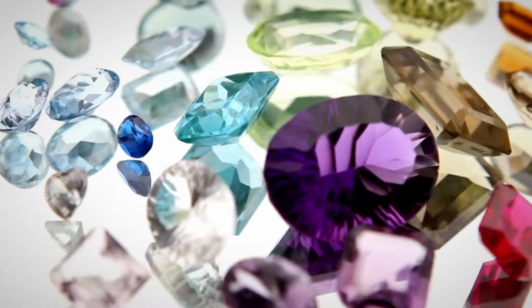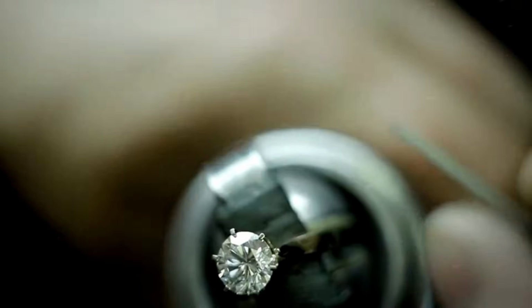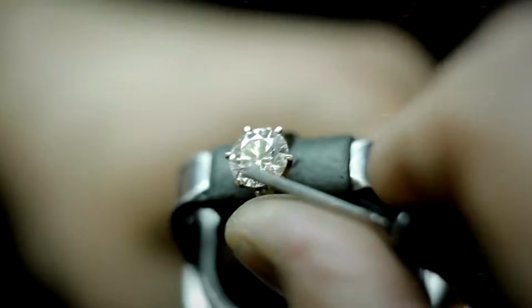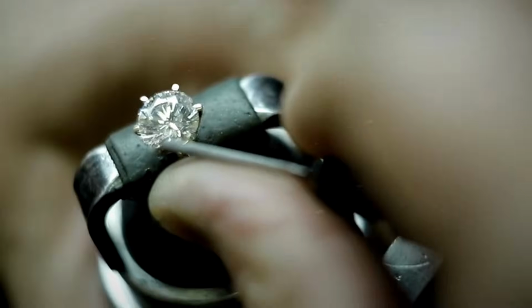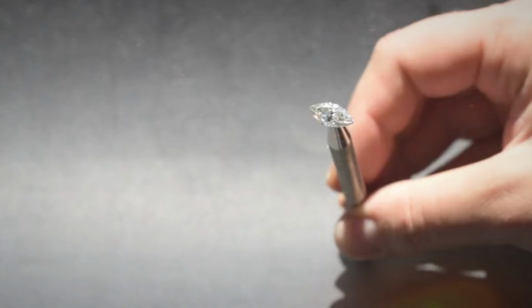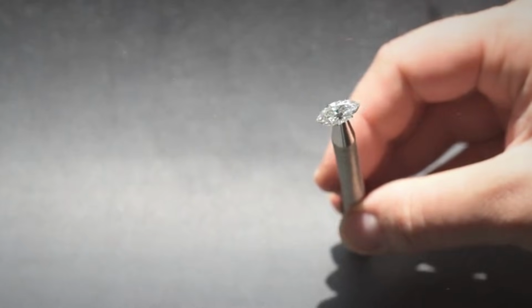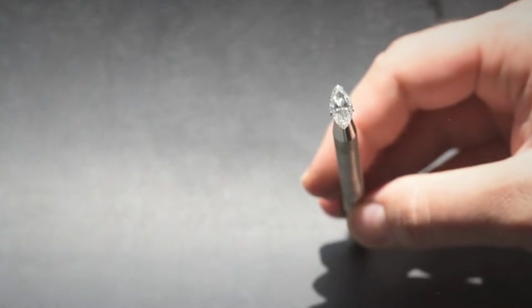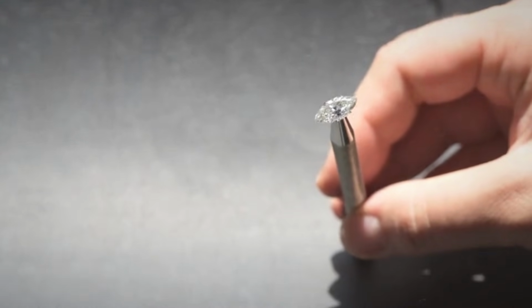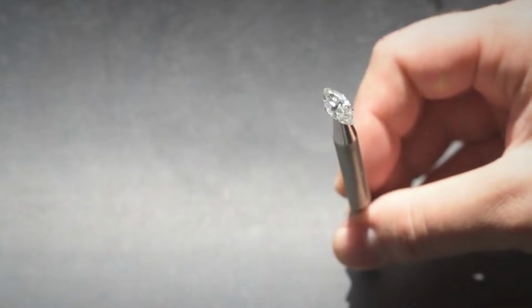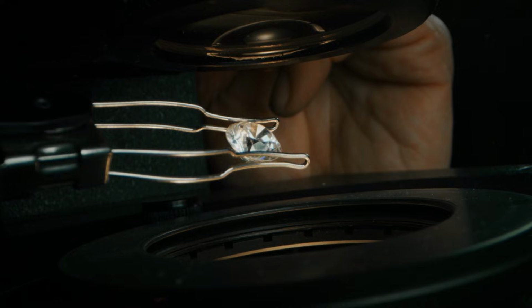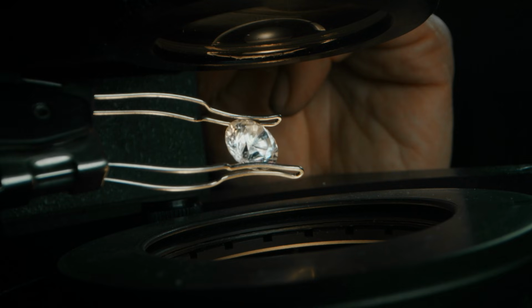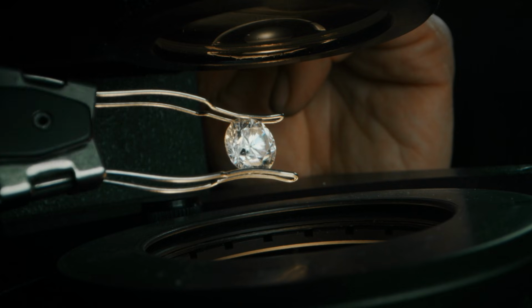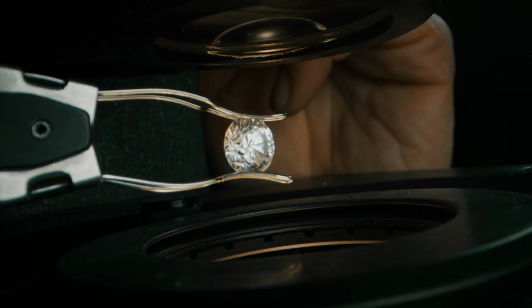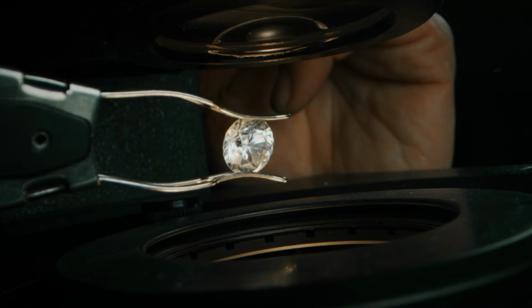However, this is only a first-tier confirmation for one reason: moissanite. Engineered to closely mimic diamond's thermal behavior, moissanite often passes thermal tests, particularly with older or low-sensitivity devices. That means a positive result doesn't prove authenticity. It only narrows the field. What it does do, however, is eliminate dozens of low-value pretenders in seconds.